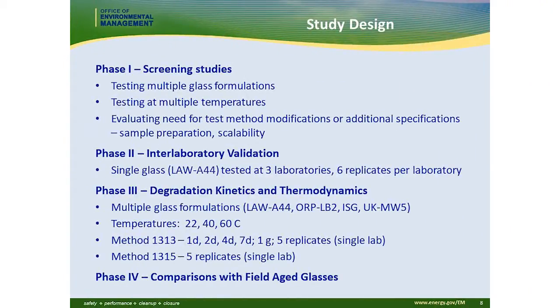So the study design was in multiple phases. The first was a series of screening tests, testing multiple glass formulations at multiple temperatures and evaluating the need for test modifications. What we found as we went forward is that there are some differences in sample preparation, and also, when working with glass, these methods were originally designed for sample sizes on the order of 20 grams or more per aliquot.